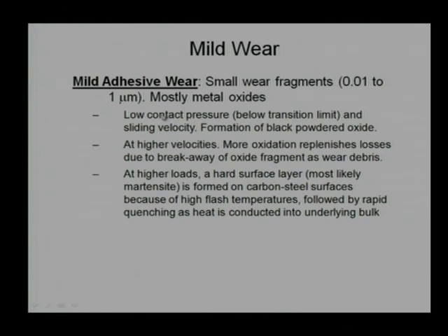Now, what are the characteristics? We are saying that the applied load is relatively low, that is why the contact pressure is low, and it is always below the transition limit; it is not even touching the transition limit. Whenever we open particularly a ferrous component, we can find some black colored powder, mostly iron oxide, which comes out because iron has a natural tendency to form oxides in the environment. So,